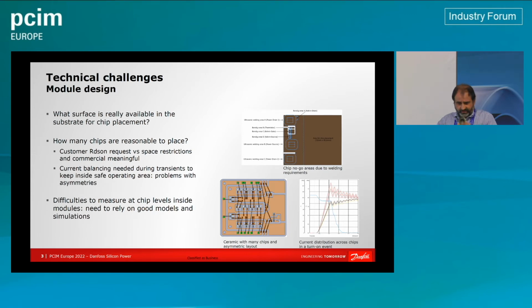So what are the technical challenges in module design? First of all, one of the important things is what surface is really available in the substrate to place the chips. In the example that I'm showing you here, you can see a big part of the substrate that has to be left open without being used for chips, because you have, for example, to do the ultrasonic welding of the feet there, and in order to preserve the cleanliness and make sure that there's no debris around it, there's a big price to pay as far as substrate space is concerned.